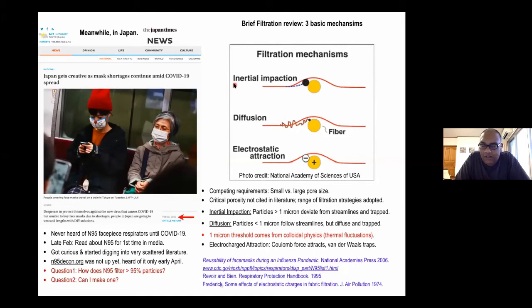And this document explains that basically there are three primary mechanisms. First is inertial impaction, the second is called diffusion, and third is called electrostatic attraction. When your particles have 1 micron or larger diameter, the understanding is that these particles can deviate from streamlines, the hydrodynamic streamlines, and then they slam into the filtration fabric and they get trapped there. But if the particles have 1 micron or less diameter, then they follow the streamlines, but they are susceptible to thermal fluctuations, and so they diffuse, and then they can get trapped by the filtration layers.